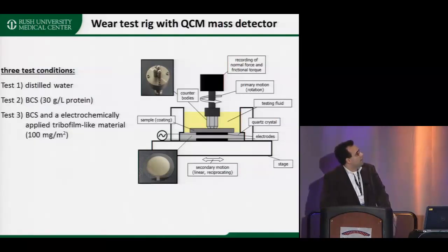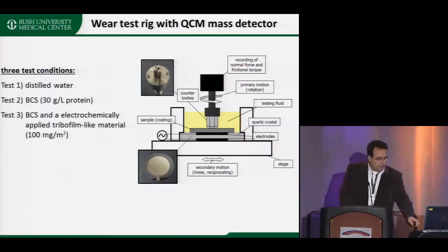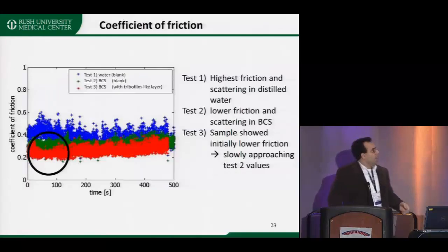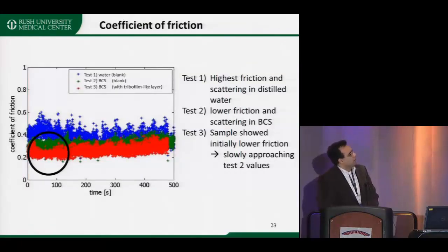So in our pilot test, we had three different testing conditions. We had one in distilled water, we tested in bovine serum, and the third test was in bovine serum, and we pre-applied, electrochemically, a tribofilm-like layer. Let me first show this plot which shows you the friction, and you see for the first test in water